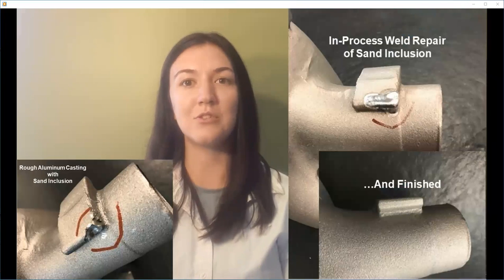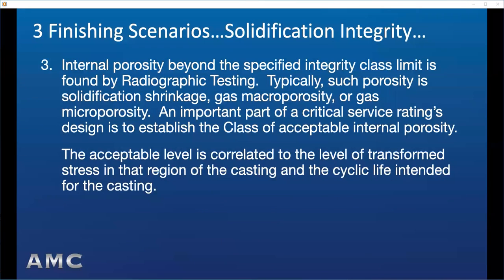and surface finish conformance. Third, internal porosity beyond the specified integrity class limits is found by radiographic testing. Typically, such porosity is solidification shrinkage, gas macroporosity, or gas microporosity. Radiographic standards for the various casting alloy types are established for these types of porosity and the standard grade levels of severity for each type.